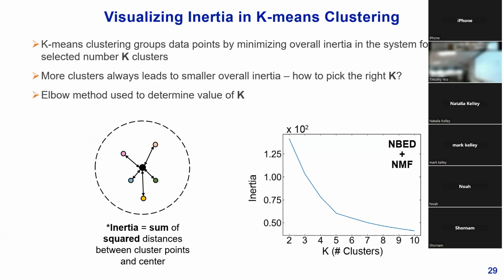And so how do you pick that number of k clusters? Well, if you plot inertia versus k, you can look at where the slope initially significantly decreases. And we take that little point right there and that corresponding k value, and we can pick that as at least a good starting point or at least an ideal initial test case for k. And so this is called the elbow point method.